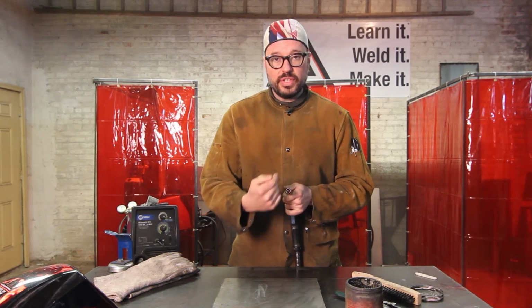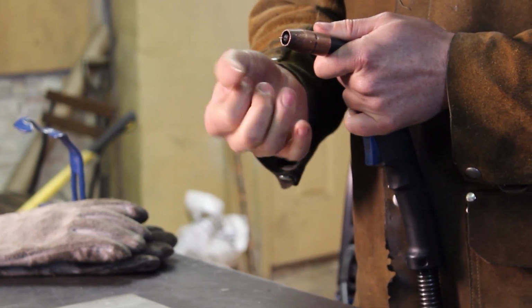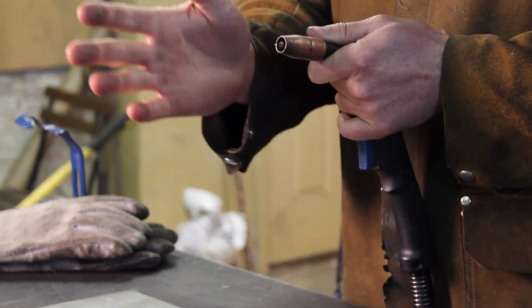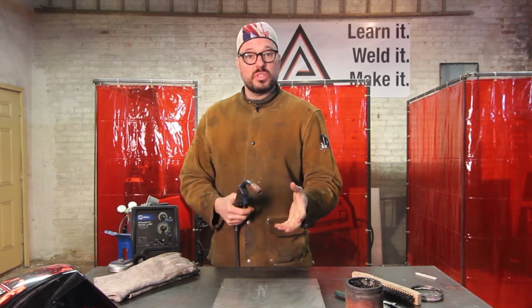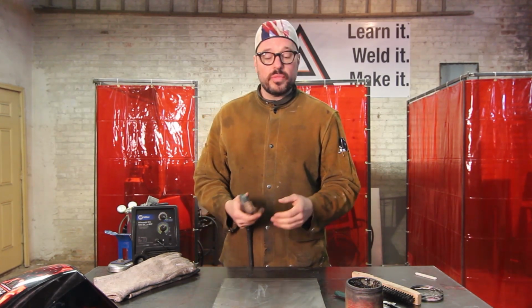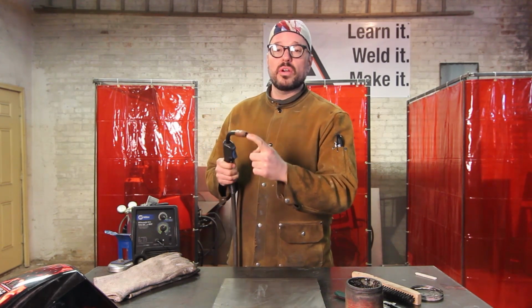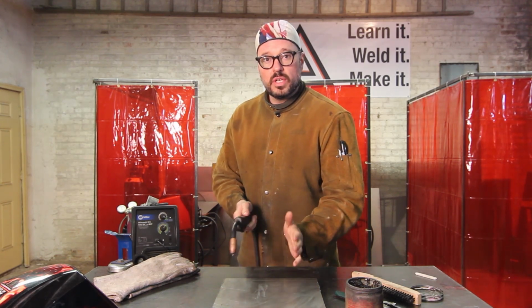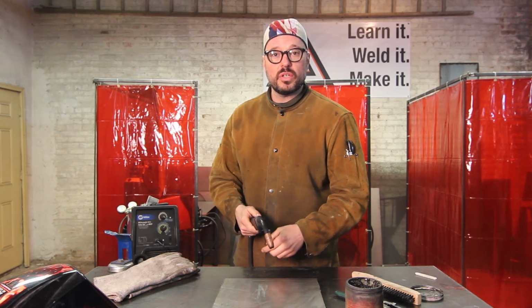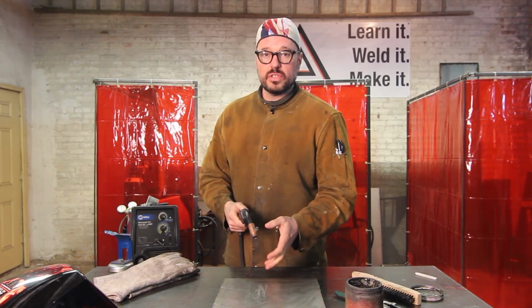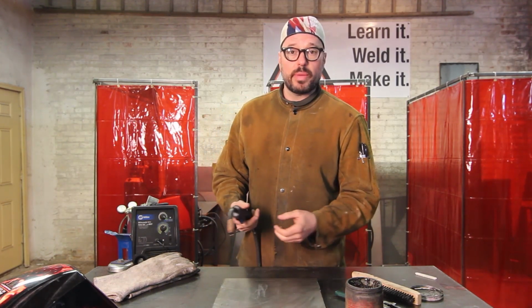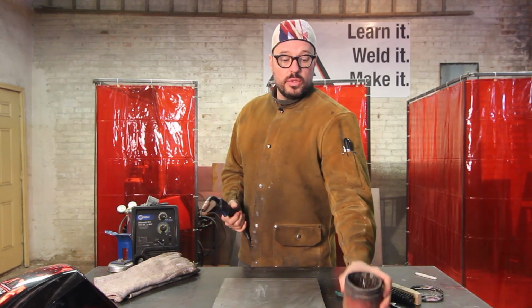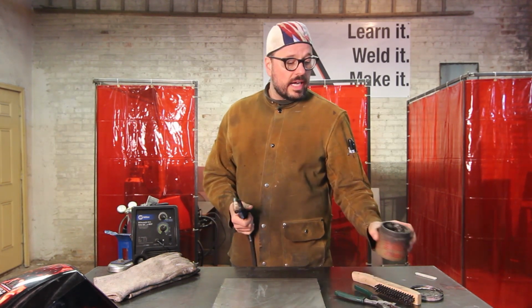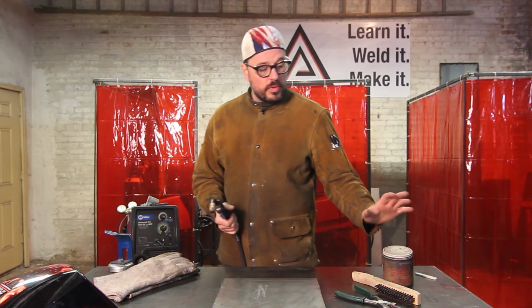Another reason, buildup reduces your shield gas port. The face of where your shield gas is coming out, it reduces that. So what happens? Well, you reduce your shield gas, it becomes turbulent or what have you, poor welding. So that's also something to consider. If you build up enough spatter on the inside as well, you're moving through the weld zone, you accidentally knock this, it falls into your weld zone, you got contaminated steel falling into your puddle, again leading to bad welding. So try to avoid all that. Use this stuff, it's great, it works. I highly recommend it. Okay, so that's tip dip.